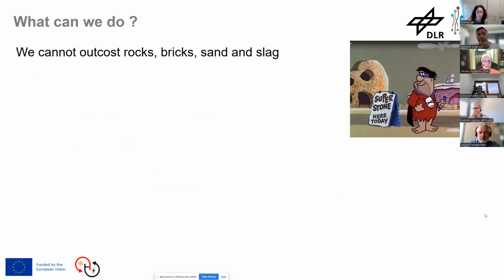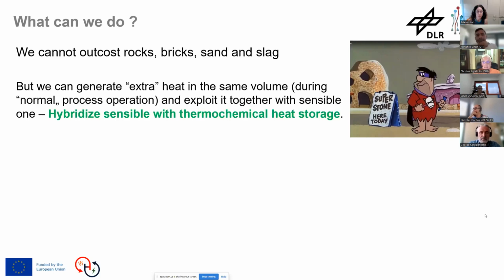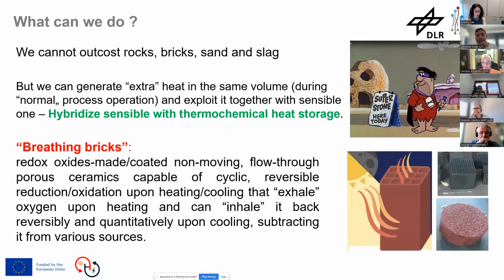Okay, what we can do, of course, we cannot outcompete bricks, rocks, sand, and slag on cost, which have also been examined as alternative solid storage sensible heat media, but we can generate extra heat in the same volume during normal process operation and exploit it together with the sensible one, and essentially hybridize sensible with thermochemical heat storage. That's our approach, okay? So essentially we pass from the so-called plain bricks to what I like to call breathing bricks, which are essentially redox oxides made or coated non-moving flow-through porous ceramics, and the feature is that they can release oxygen upon heating, remain in the solid phase, and then inhale back this oxygen if, for instance, air is passed over them to again generate heat through the reversible exothermic oxidation reaction.